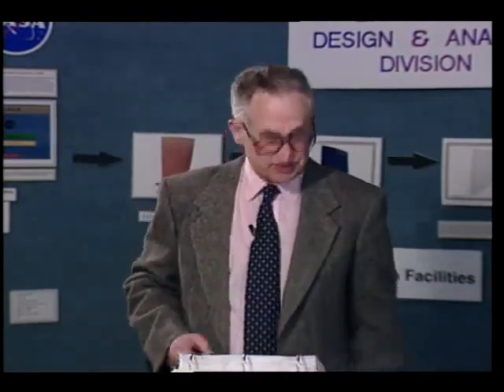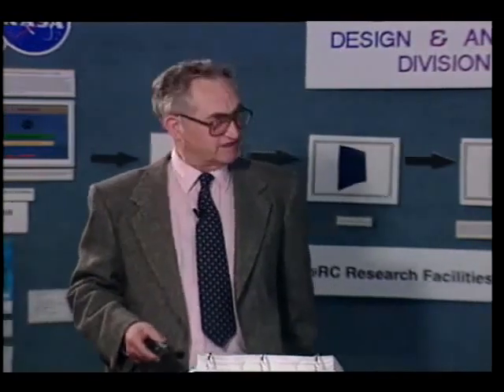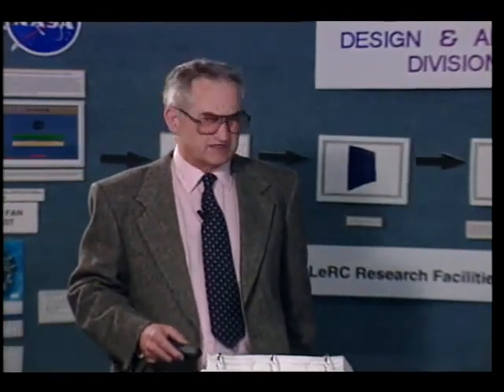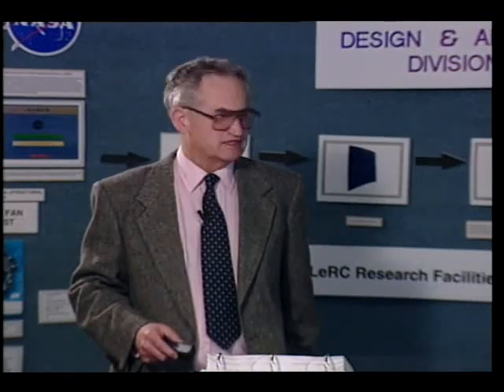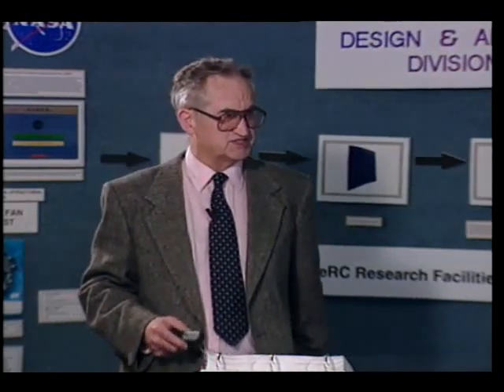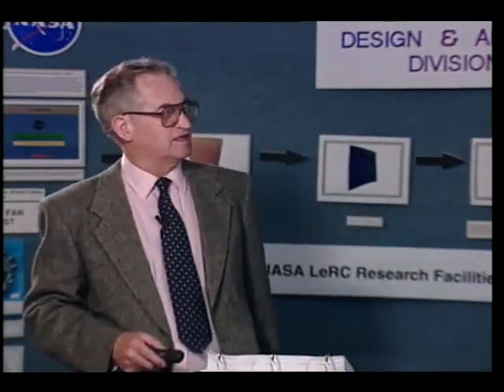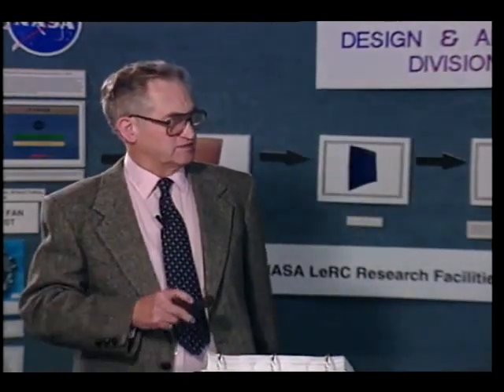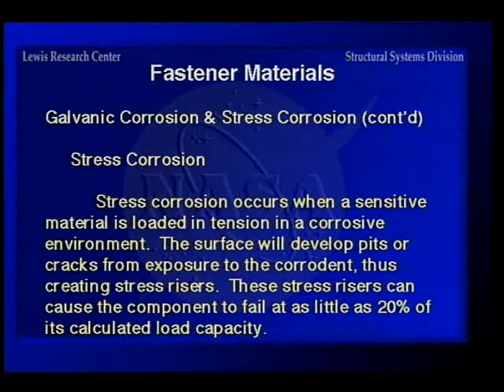Okay, now going to stress corrosion. That is something that we're all familiar with, in a sense, but there's not much available in textbooks on it, because the study of it is a fairly recent thing. Stress corrosion, of course, occurs when a sensitive material is loaded in tension in a corrosive environment. Now, that sounds pretty easy. What happens is the surface develops pits or cracks from exposure, and this gives you stress risers, which will cause the component to fail at as little as 20% of its calculated load capacity.